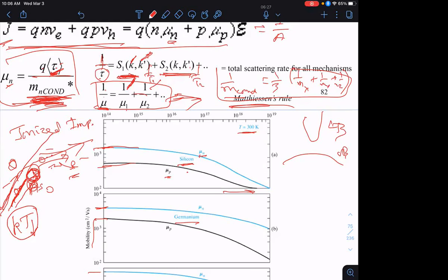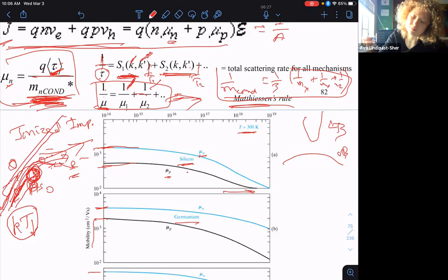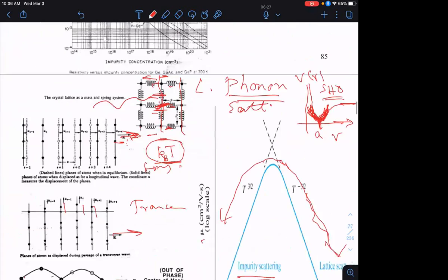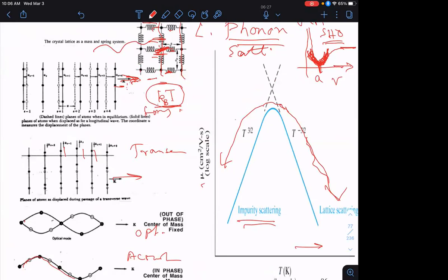So the slower electron would be deflected more because then it's going to be in the vicinity of this charge longer. While if it's zipping past, it doesn't see the effect of that much, right? So that's responsible for this drop in mobility due to impurity scattering at lower temperatures. Okay, so at lower temperatures, the electrons are more and more sluggish, and they can be impacted by these impurities more and more. While at very high temperatures, the mobility drops again because of more lattice vibration.